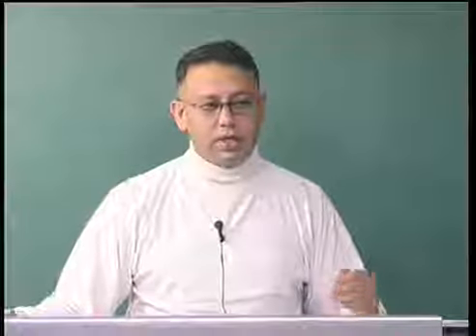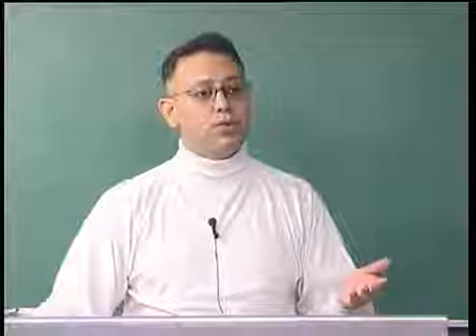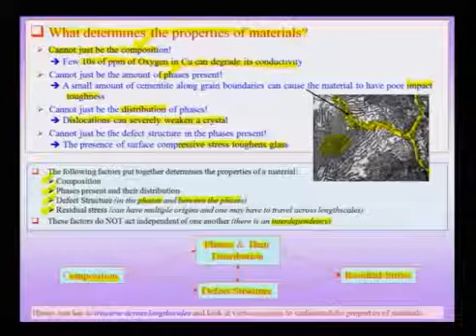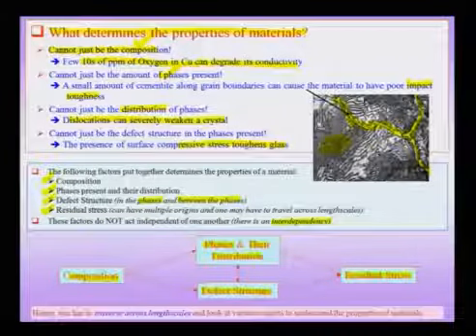Suppose we were talking about the glass and the compressive residual stress. Suppose we put tensile residual stress on the surface, then the properties would in fact be worse than that in a material which had compressive residual stress on the surface. But we will have some more look at these concepts as we go along. Therefore, if one wants to understand properties of a material, then he or she needs to consider various factors: the composition, the phases and the distribution, the defect structure, the residual stress, and in doing so has to traverse across length scales.